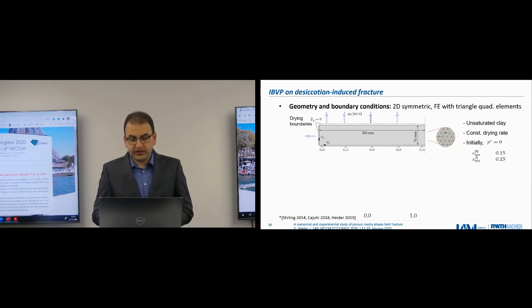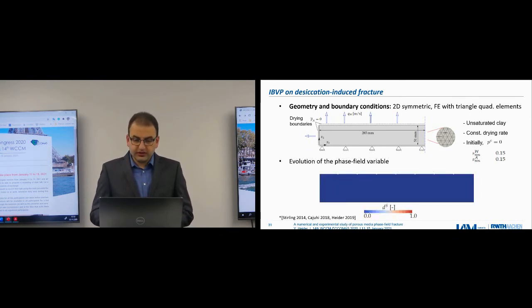Let's present one of the examples, the drying induced fracture. We have this domain, it's unsaturated clay, and we apply the drying process on this. Here, as I said, we have no temperature, so the drying would be a kind of outflux at the boundary. It's given by the flux vector QW. Initially we have no capillary pressure, and the residual saturation is 15%. When the drying process starts, we see that the cracking starts to propagate at the beginning from the bottom and then from the top, and then we get different cracks propagating at different speeds and so on.